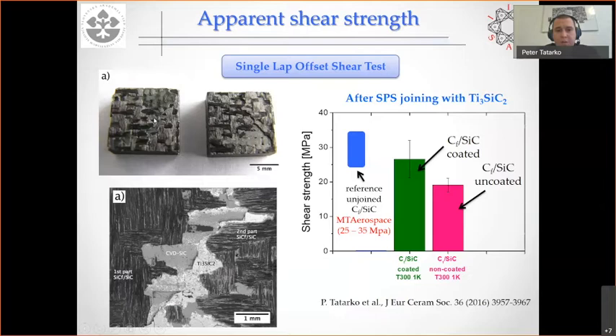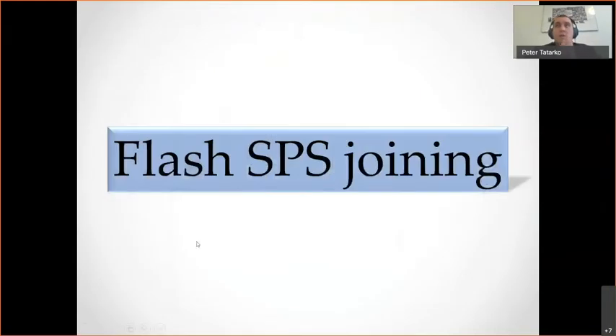If you look at the fracture surface, you can see no delamination, but the crack went from one part of the composite into the second one. So this suggests that the joint was very strong and stronger than the interlaminar shear strength of the material. So that was the result which at the beginning I called SPS joining.